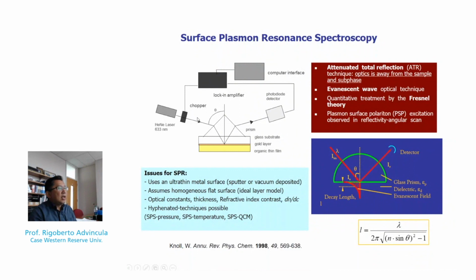Now, to integrate the whole thing in terms of sequence and waves, one has to use a lock-in amplifier, a chopper, and all the best optics to get clean waves. And then, of course, readout and control could be on the computer interface. So in short, this experiment allows us to look at the decay of that evanescent field with regards to distance from the surface, or with regards to changes in reflectivity as a function of time. So schematically, what is shown here is that over distance, the evanescent wave decays as you go farther and farther away from the prism. So this coupling means that it is sensitive to thickness changes or dielectric changes as well, as mentioned earlier.